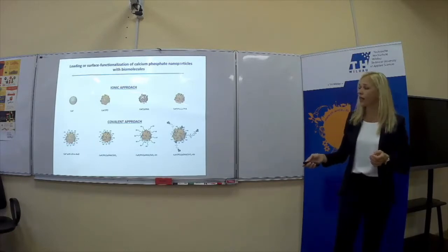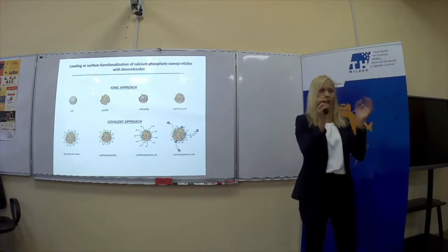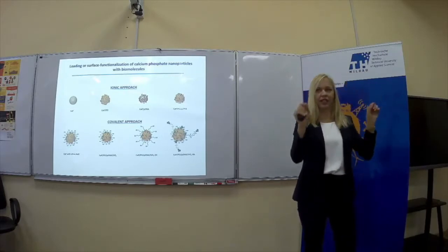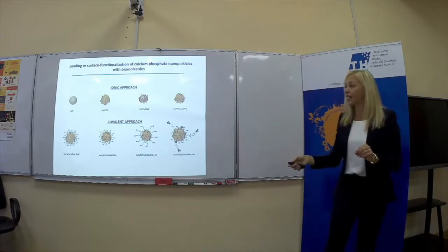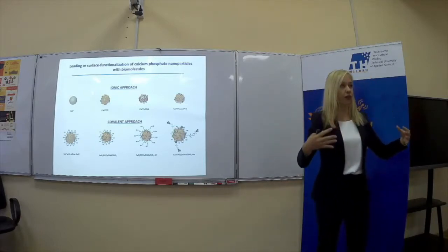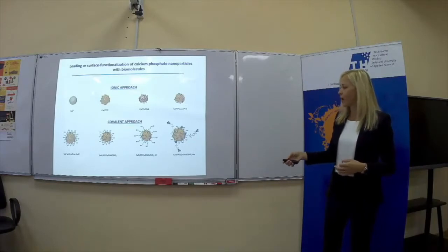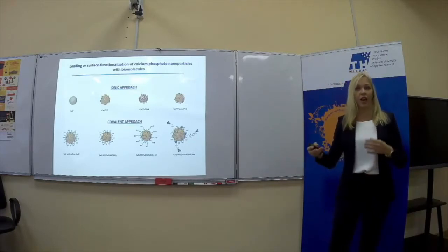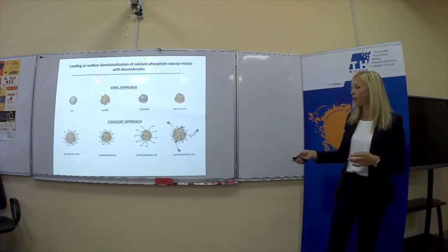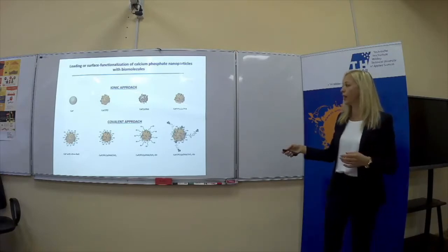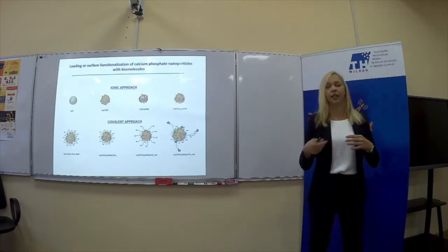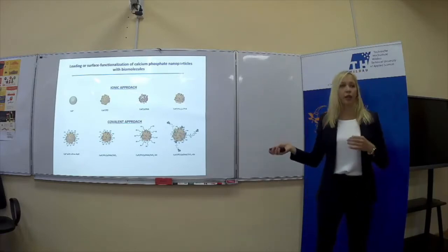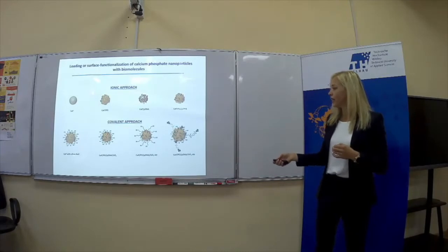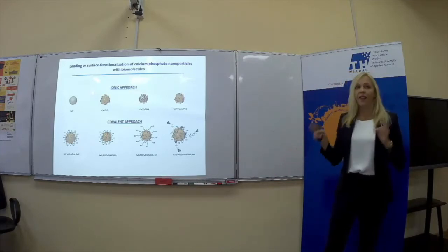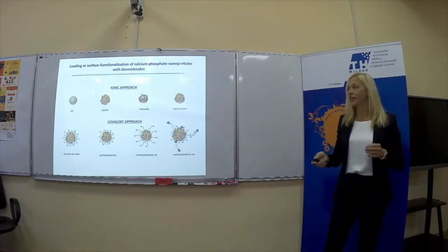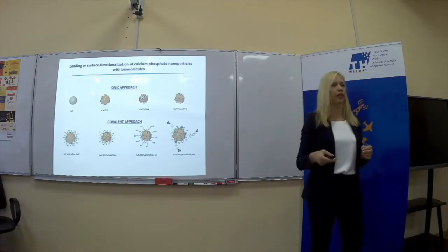The idea was to add a silica shell on the surface. You have calcium phosphate, and you have a really thin silica shell on the surface. And the silica shell you can functionalize further. For example, you can add thiol groups on the surface, and thiol groups can then be further adjusted, so you can use antibodies with a cross-linker. Different cross-linkers are well known in biochemistry, so with this interaction, you can develop very complex but very efficient nanoparticles, and we use these particles for cell targeting.